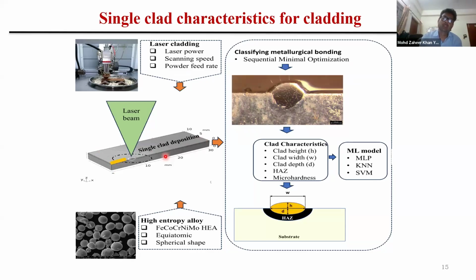This bead was actually cut across. When it was cut across, it looked like this, and this is the bead that we obtained after we cut it and polished it. So after polishing, you can see there is a clad bead that is obtained, and the remaining portion is the substrate material. So, for any proper characterization, it is important that these parameters of the characteristic bead profile